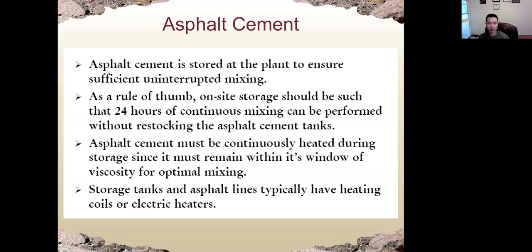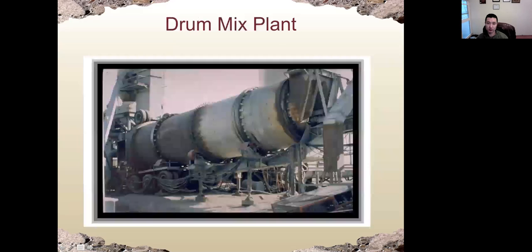Here is about the preparation of asphalt cement, the binder. Again, we need to heat it up so we can make it soft to mix with sand and coarse aggregate. And also we need to ensure we have sufficient uninterrupted mixing. We should have continuous heating of the binder during the storage process. And also we need to ensure we have enough asphalt for continuous mixing. And here is the drum mixer plant, which is the oven to heat up the asphalt binder.